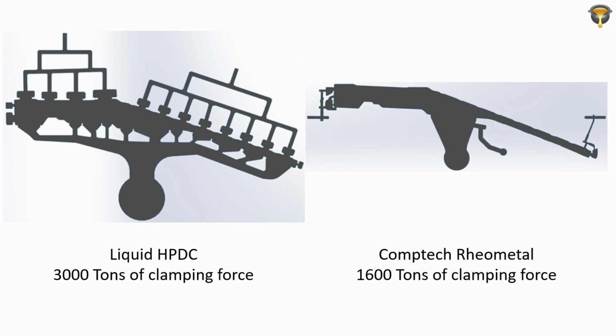But besides this, with a smaller die-cast machine, there are two effects. Number one effect is, of course, the projected area. If you have all these overflows and all these in-gates, you have a bigger projected area around the part than the part itself. In Rheocasting, we work with much less gating and overflow, so we take out projected area. That's effect number one. The second effect is that you take out mass in the gating and overflow system, so there's less material to melt. That's an important factor.